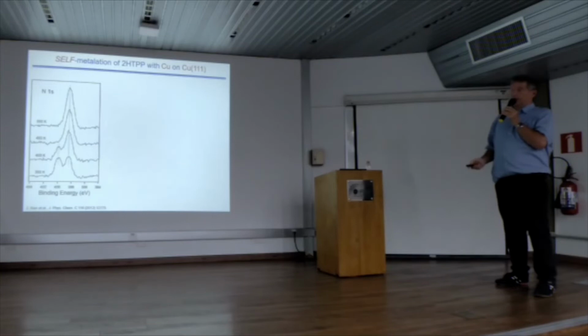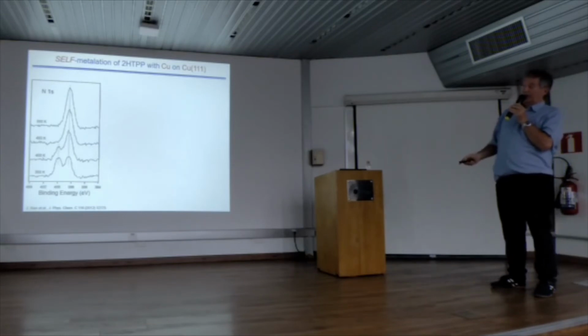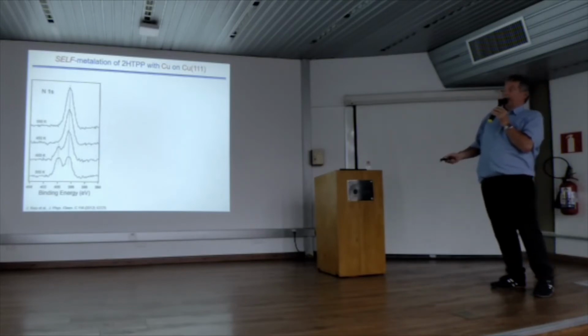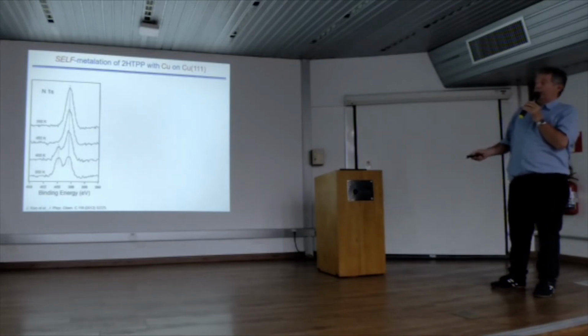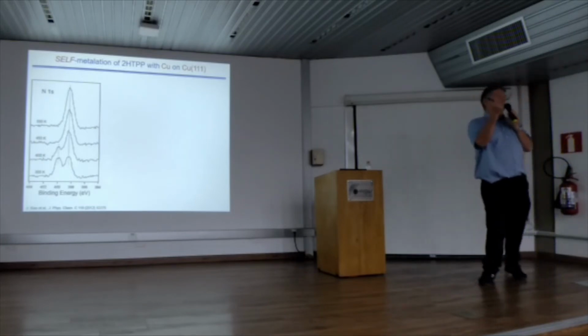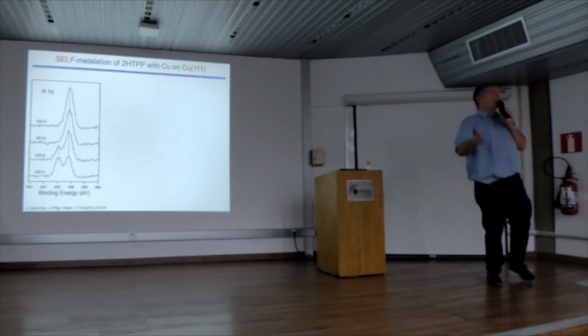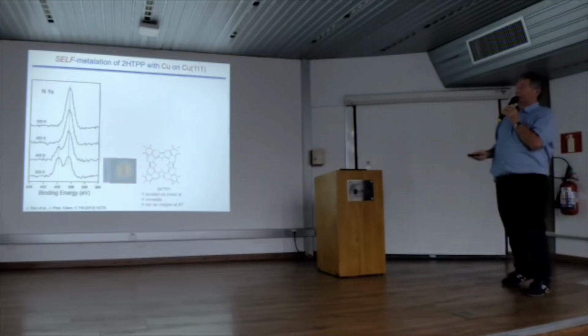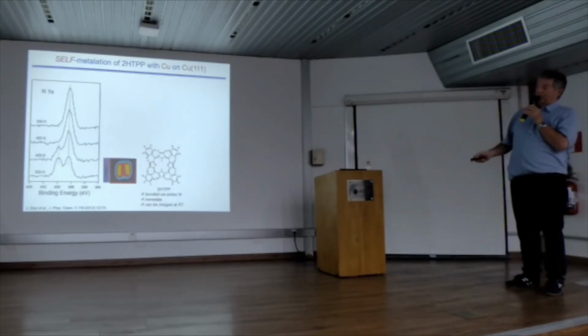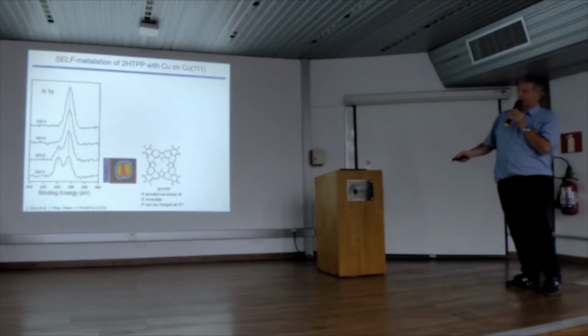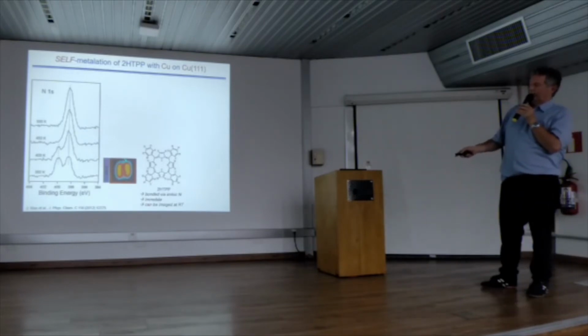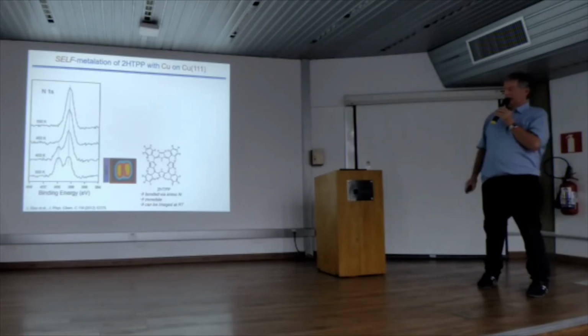And indeed it is. So if we deposit at room temperature, where we did our diffusion experiments, we saw no reaction, and in the XPS we see the 2 peaks. But as we heat to 450 Kelvin, we see only 1 peak. So obviously, it picks out the copper atoms from the substrate, or takes atoms from a 2D gas of copper atoms on the surface, and inserts them in the species. And in STM, you remember, this is the 300 Kelvin species, with this longish dark line in the center. And this species we could image at room temperature.